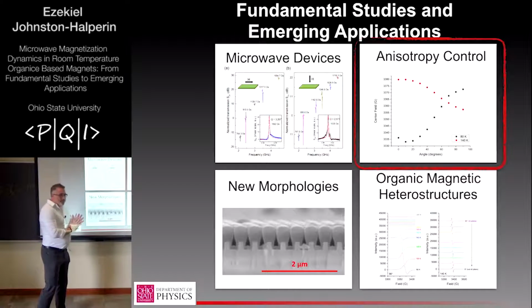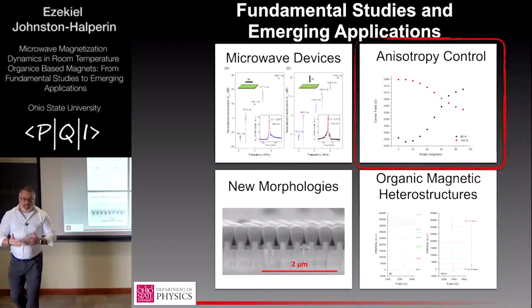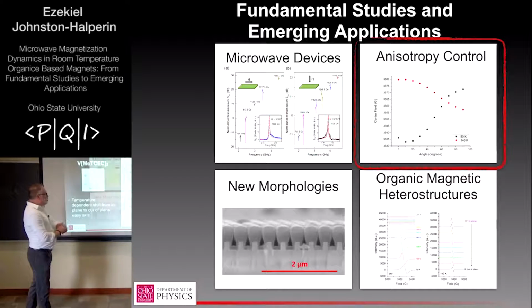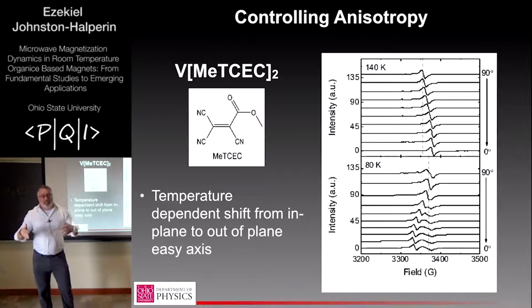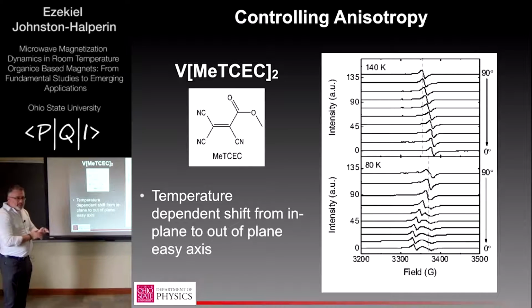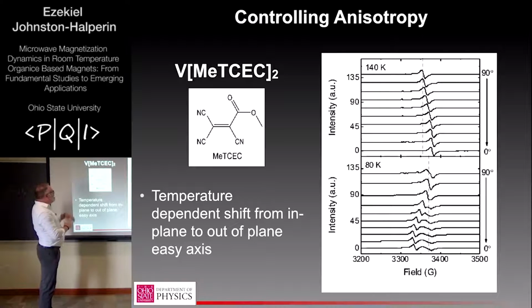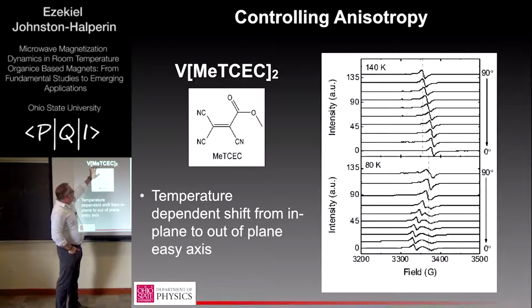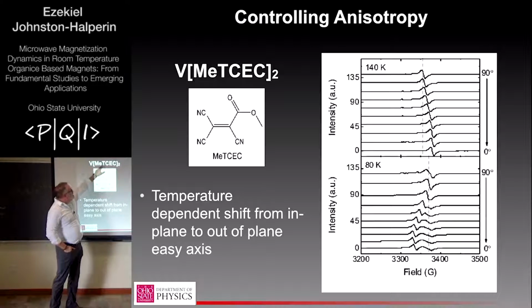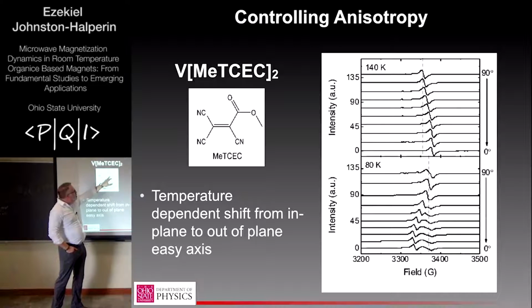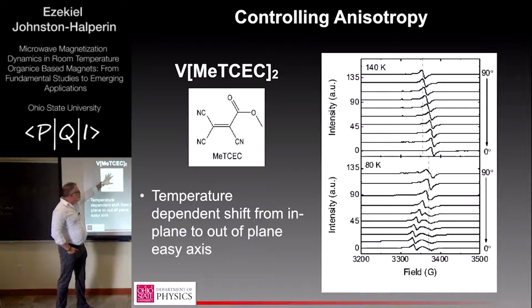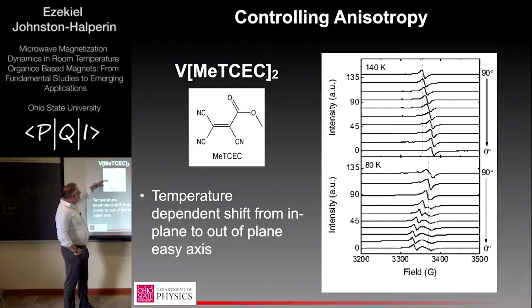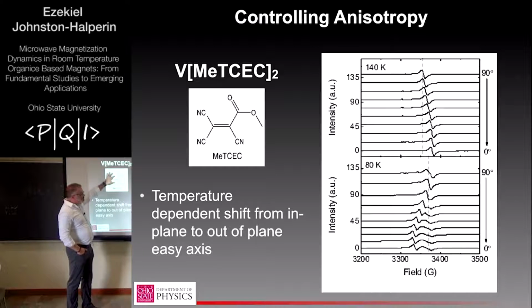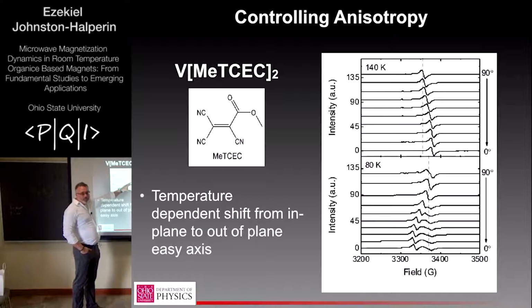So this was happening simultaneously with another experiment that was exhibiting anisotropy at the same time. This is a related compound, vanadium MeTCEC. The translation of that is you take a TCNE molecule and you replace one of the cyano groups with a carboxylic acid, or a carboxyl group, excuse me. And so this changes the electronegativity, it changes the bulkiness or the steric nature of this ligand, and it removes one of these binding points for vanadium.